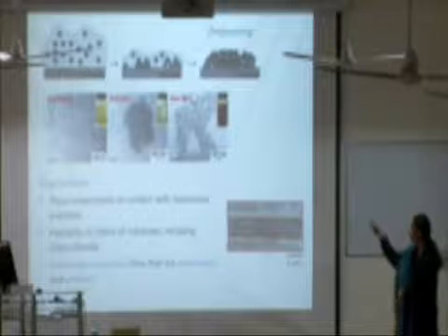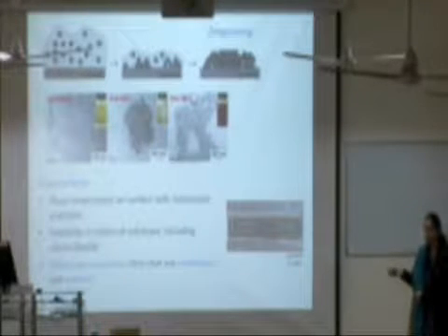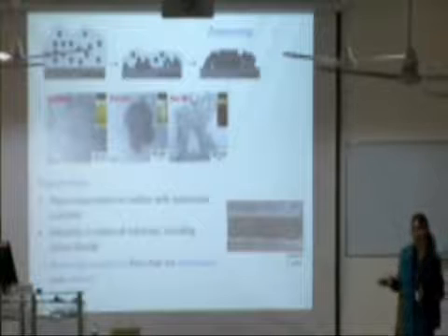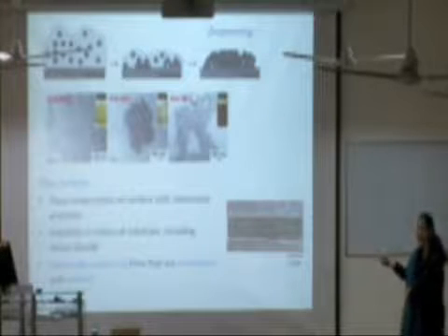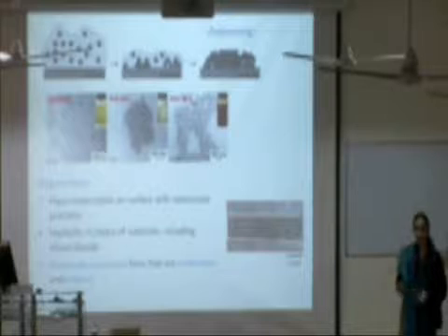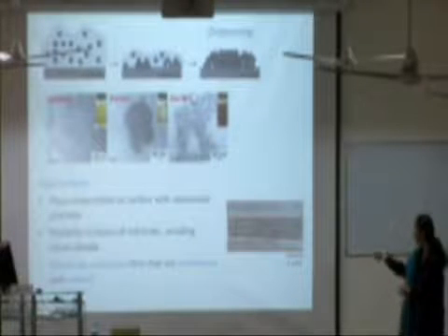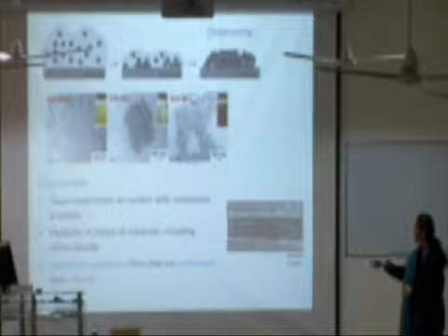The problem with these films is that here I show you a scanning electron microscopy image of a film over a large length scale. So there's cracking that's visible in these films. So if you're studying transport in such cracked films, obviously you will not know if you're dominated just by the grain boundary scattering or some other thing that is clearly not visible in this figure.